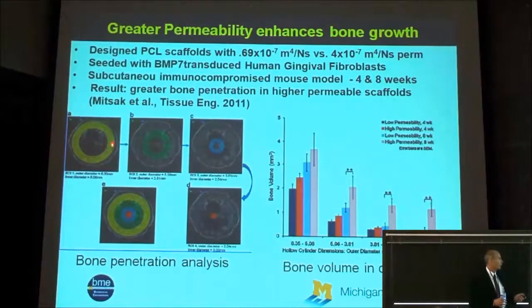And then we did micro CT on the results at 4 and 8 weeks. And we did this ring analysis where we could look at not only how much total bone is in the scaffold, but how well the bone penetrates over time into the interior of the scaffold. And what you see here is the low permeability scaffold at 4 weeks, high permeability at 4 weeks, low permeability at 8 weeks, and high permeability at 8 weeks, in the outermost ring, second outermost ring, second innermost ring, and the innermost ring.